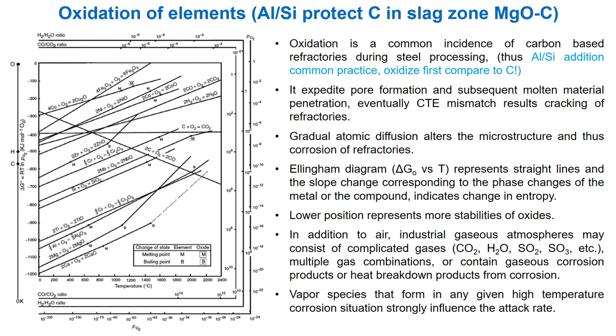The importance of oxidation study can be discussed by considering carbon-based refractories, where refractory manufacturers use aluminum or silicon metal powder to protect carbon. The obvious high stability of oxide is not the only reason — in-situ formation of corresponding carbides of aluminum and silicon also influences the properties at high temperature. Oxidation expedites pore formation and subsequent molten material penetration.